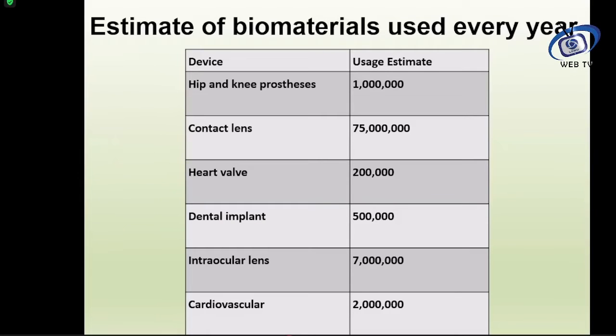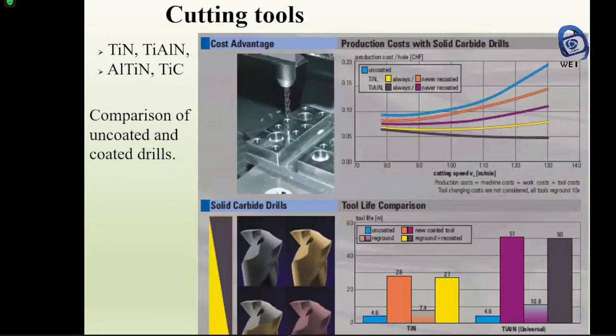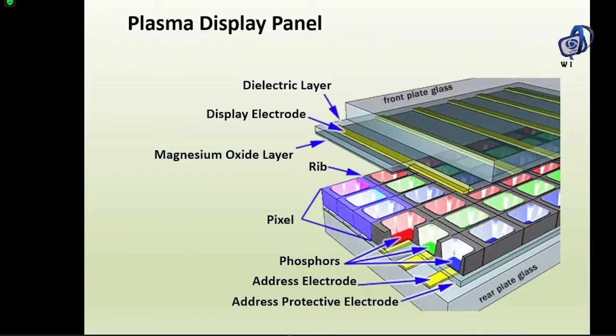About 1 million people have been using that, and with plasma we can make surfaces bio-friendly. We can deposit hard coating films: titanium nitride, aluminum nitride, titanium carbide. We can see that the hardness of the film is increased, so the life of the tool has increased.